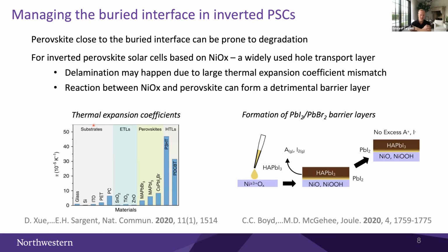One critical interface is the buried interface in the inverted devices. So this corresponds to the HTL perovskite interface. Here nickel oxide is widely used, but there are challenges. One is the potential for delamination. Another is reactions that can occur at this interface.